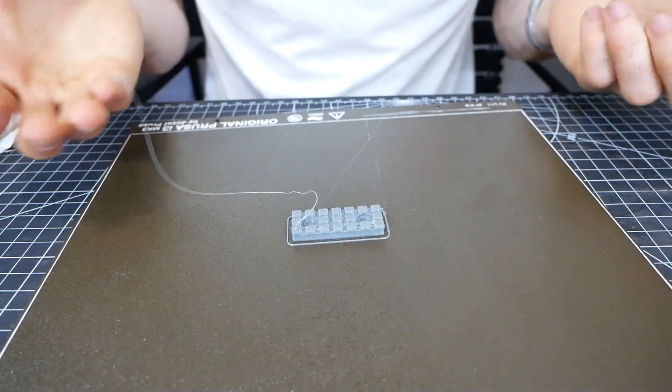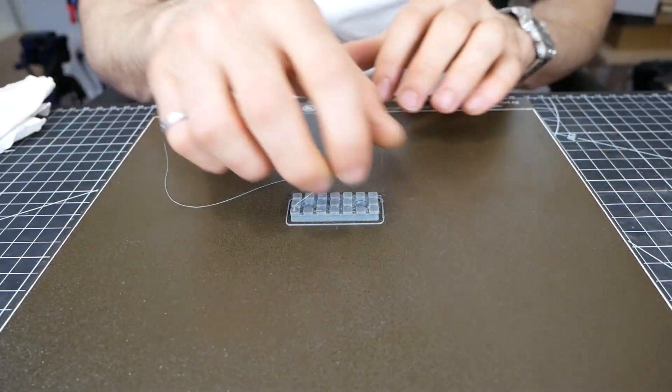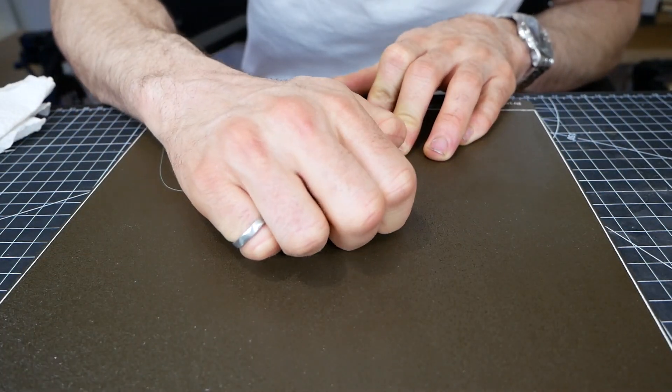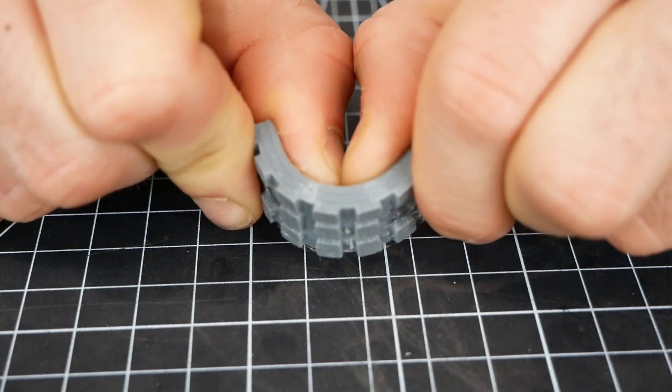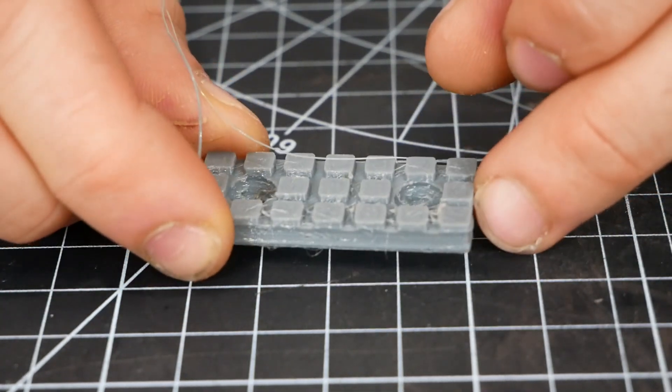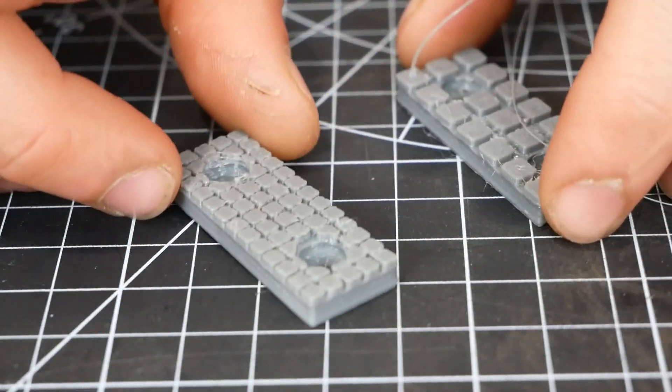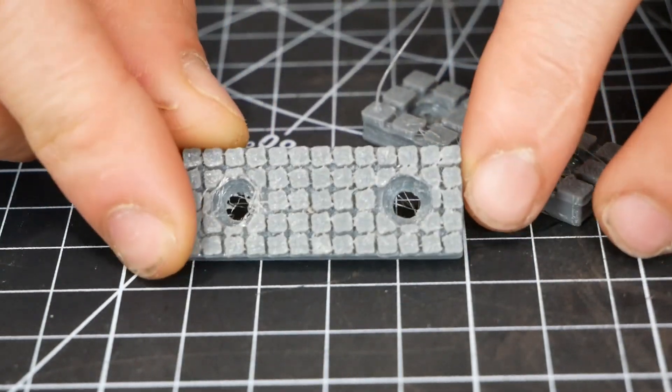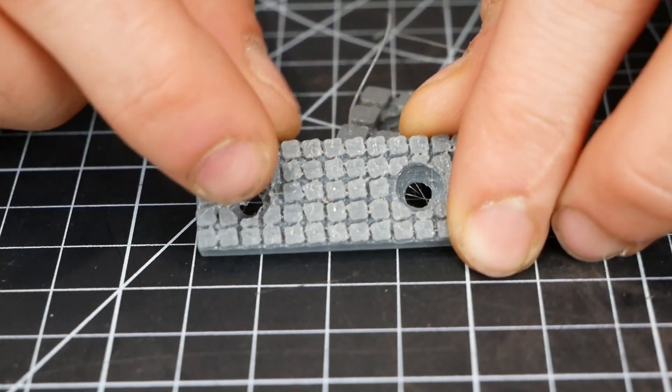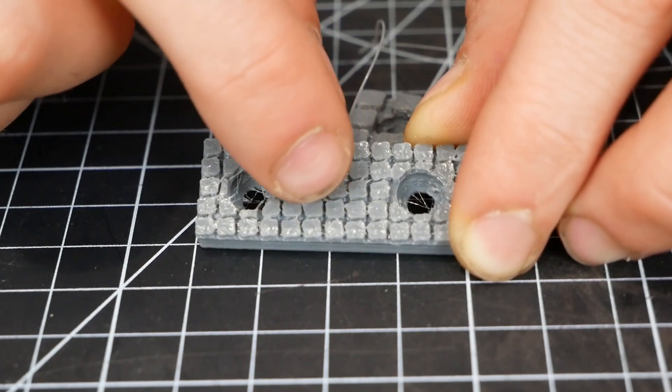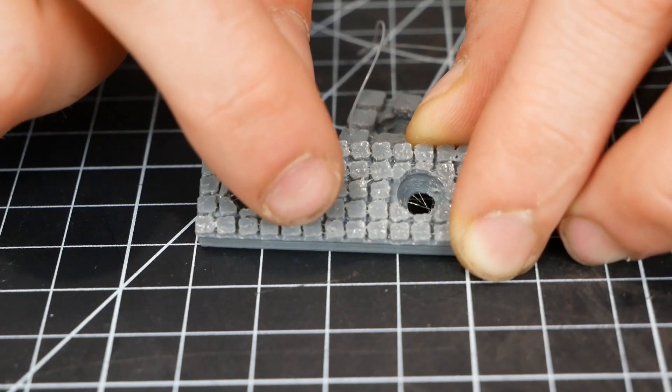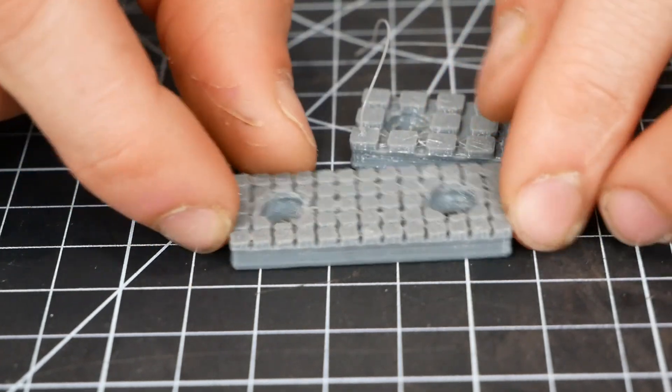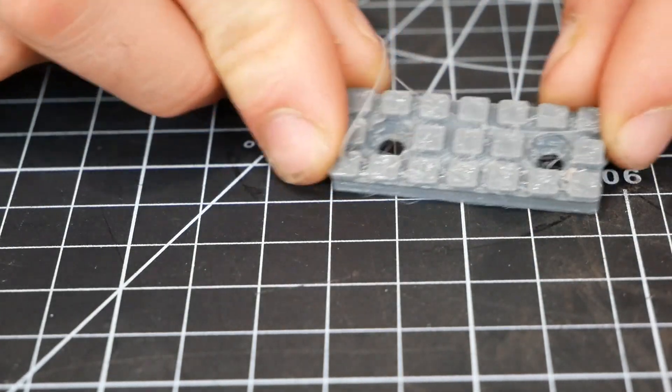So TPU prints can be pretty difficult to get off the build plate. You can't just flex it like a normal rigid print and expect it to pop off, because it's flexible - it's just going to flex with the bed. So sometimes you got to apply a bit of force. Check it out - bendy! It's pretty common with TPU to get a fair amount of stringing, but altogether I am happy with that quality. This was one of my earlier prototypes - I was trying a much smaller tread pattern. As you can see, each tread kind of got skewed around in a circle. The nozzle was moving around each of these squares counterclockwise, and I think because the filament wasn't cooling very fast and because it's flexible, it was sort of pulling each square around in a circle and skewing it. So printing small details like these can be really difficult with TPU, so I just opted to use a larger tread pattern.